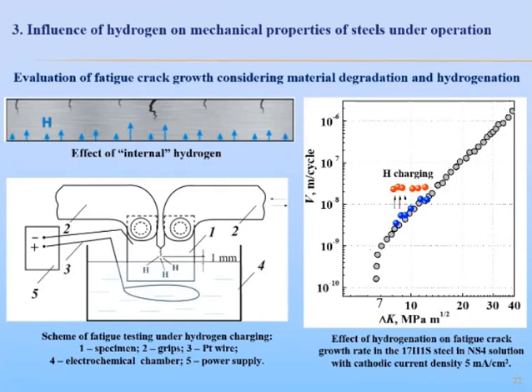As you can see, only the lower part of the specimen was subjected to electrolytical hydrogenation, and at the same time, the upper part of the specimen was with a growing fatigue crack. The fatigue crack was in air, and hydrogen absorbed by the metal due to electrolytical hydrogenation moves by diffusion to the crack tip and affects the crack growth rate.